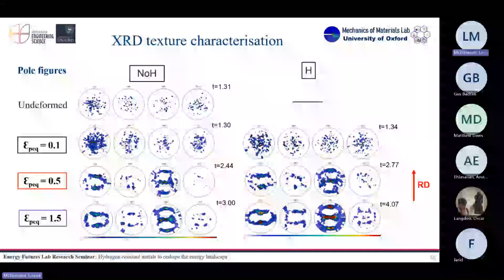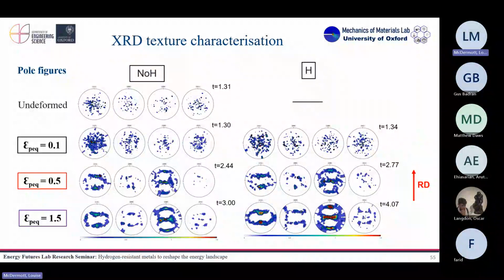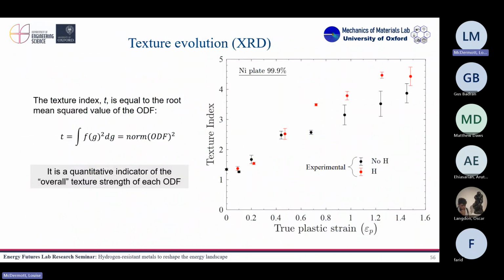So we went to XRD measurements, where you measure the bulk of the material, and we obtain the pole figures, which are another measure of the texture. With these pole figures, you can do some kind of average between them and get a number called the texture index, that gives you an overall strength of the texture, of how strongly the material is texturized.